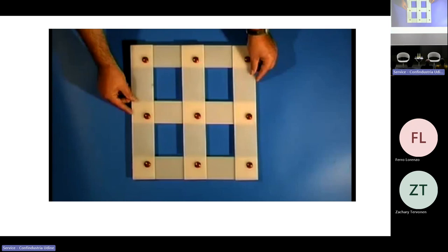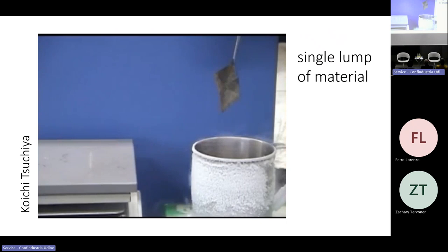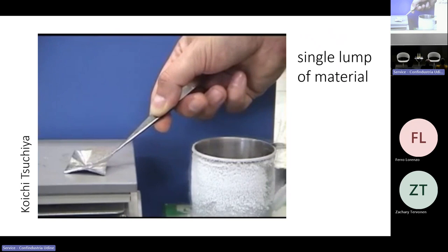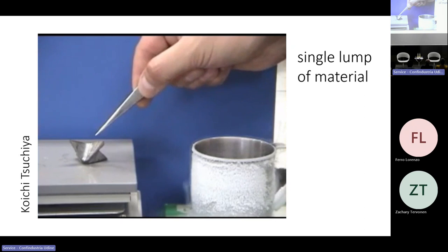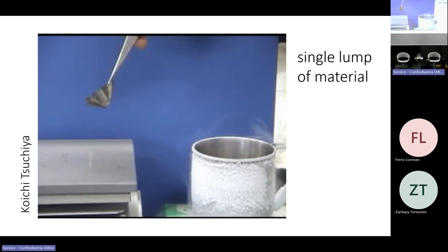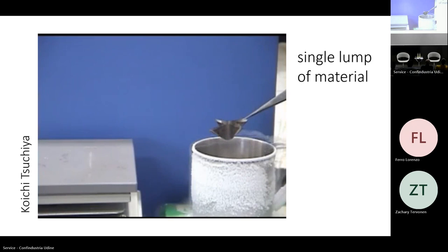And that is very interesting because it gives rise to an effect known as the shape memory effect. And I'll illustrate that effect here. This is not actually steel. This is nickel titanium alloy. And it changes its shape as you change the temperature. So that's a hot plate. And you can see there's no engineering inside that lump of nickel titanium. It's just nickel titanium, all right? And then when you cool it again, it reverts to its original shape. So it retains a memory of its original shape. So you can see it reverses its shape.